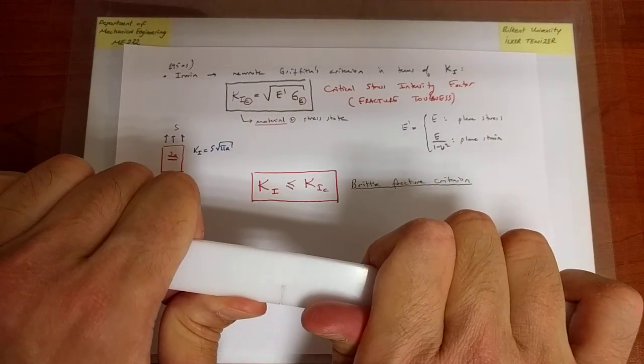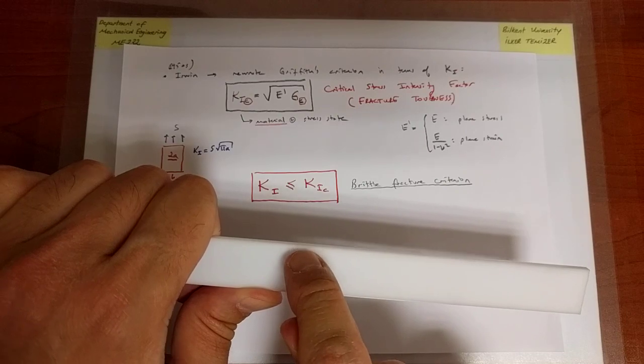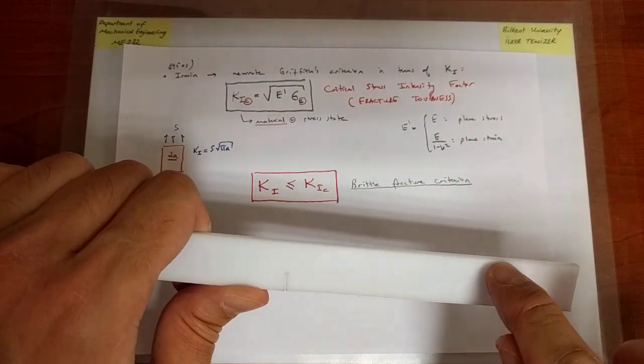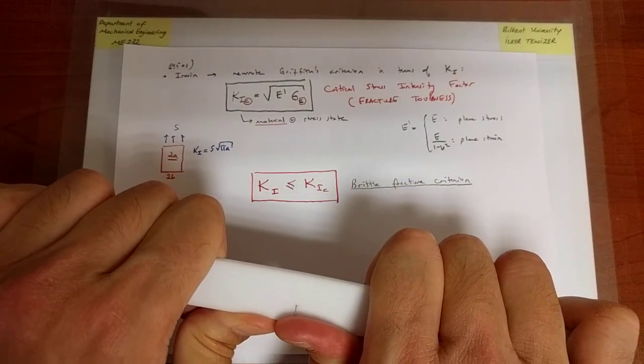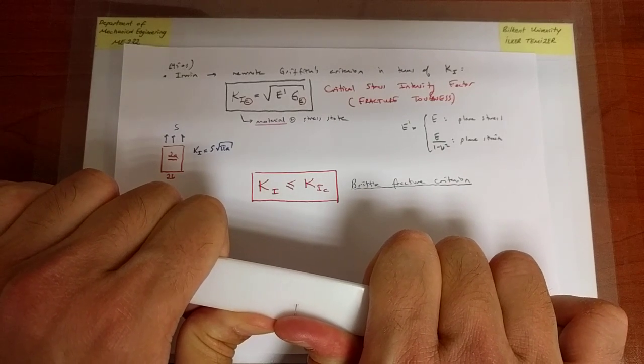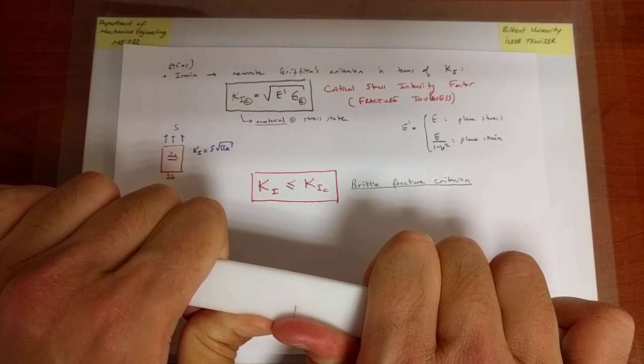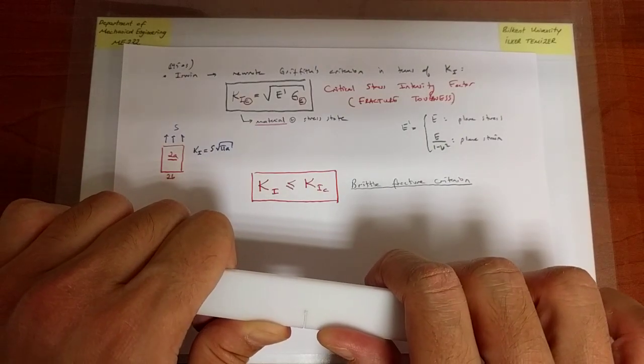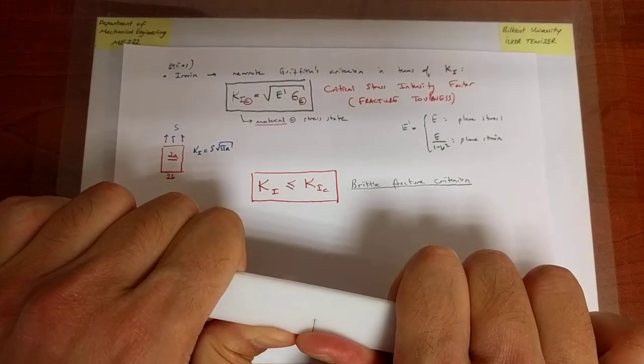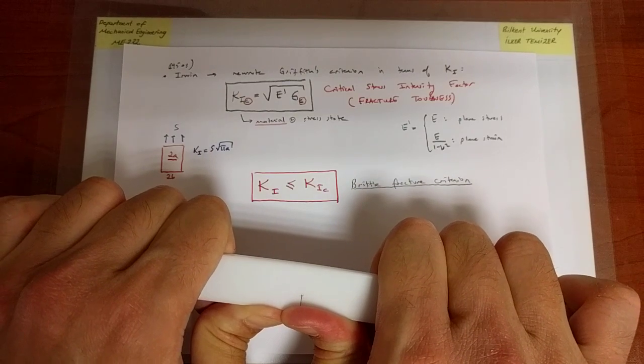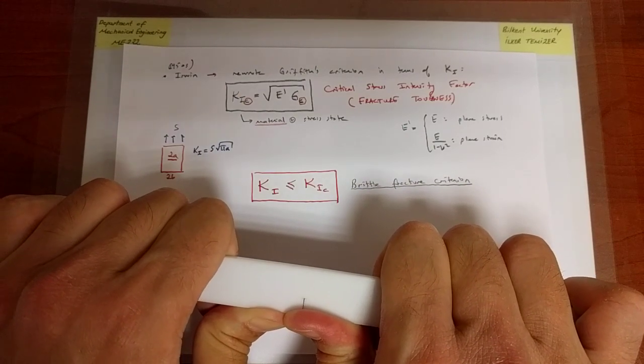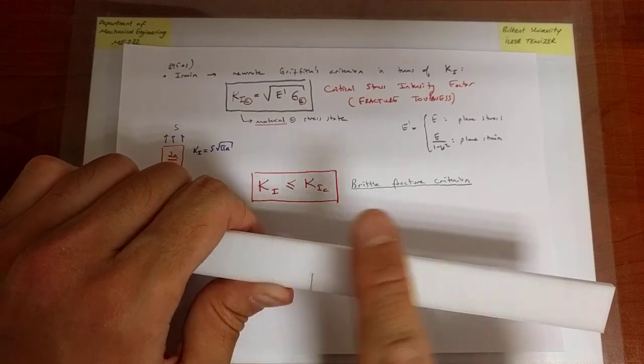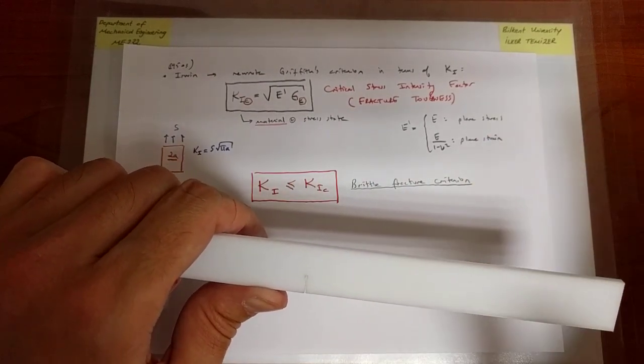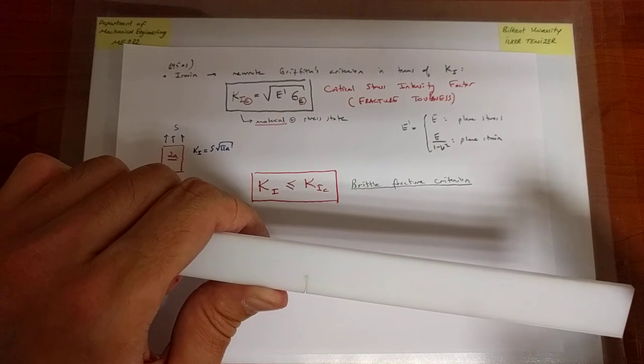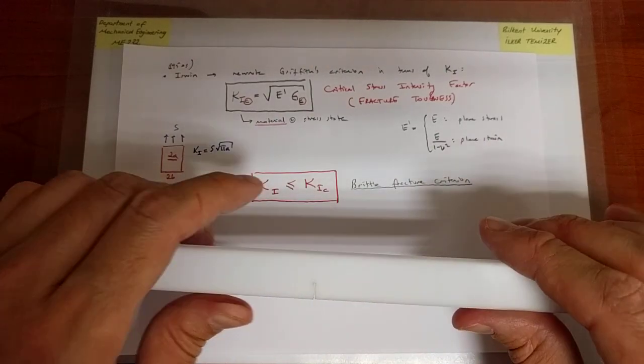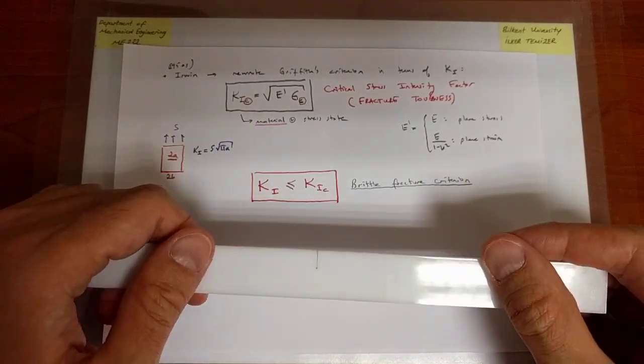When I'm trying to bend, that's where the maximum tensile stress occurs, and this is a brittle material, it turns out. I'm trying to reach the ultimate strength of the material, and the ultimate strength is actually quite high, and I cannot reach that value, and hence I cannot break the specimen. So fracture, the way we are discussing it, does not have to do with reaching the ultimate strength. It's an entirely different process, and to demonstrate that, now I'm going to flip the specimen over